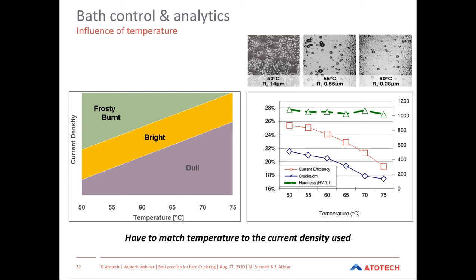So in order to avoid this roughness, by increase of temperature, you would move back into the bright area, and this roughness will be reduced or removed. With the HEEF type processes or Dynachrome type processes, this increase of temperature and the resulting drop of hardness is not happening. It will happen with a Sargent type or conventional baths. Increase of temperature there will result in a drop of hardness, but the catalyst system in the HEEF process is avoiding that, so no hardness drop with increased temperatures with the HEEF system.